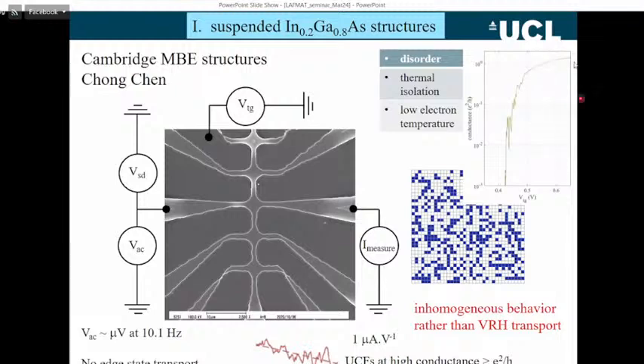When we reduce the carrier density with the gate, the system breaks up into a series of islands. So it becomes non-ergodic, breaking up into a system of little electron puddles. The current through the system is just transport between these islands of charge, which is a so-called Coulomb blockade. So it goes over to being a Coulomb blockade system, and we see this kind of inhomogeneous behavior. We don't see variable range hopping transport, even though we've put disorder in and we're at low temperatures, at low electron temperatures. The system goes over to an inhomogeneous system.